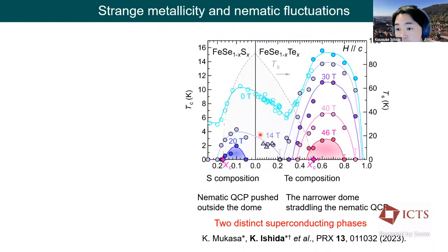Distinct superconducting phases are further supported by the separation of these two domes under high field, where the nematic QCP of the sulfur side is pushed outside of the dome. This suggests that the spin fluctuation is more dominant over the nematic fluctuation in the pairing mechanism. But in contrast, the dome of FeSe-Te keeps straddling the nematic QCP until the superconductivity is completely destroyed. So this indicates that nematic fluctuations play a key role in the pairing mechanism in FeSe-Te.